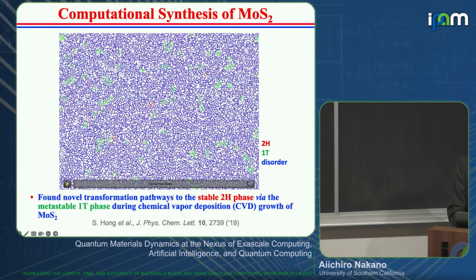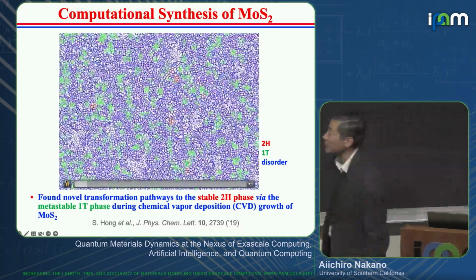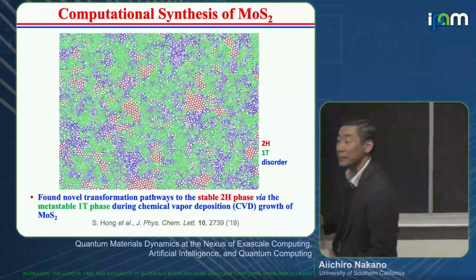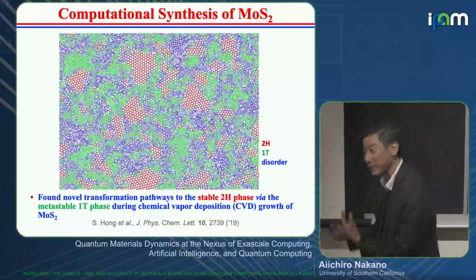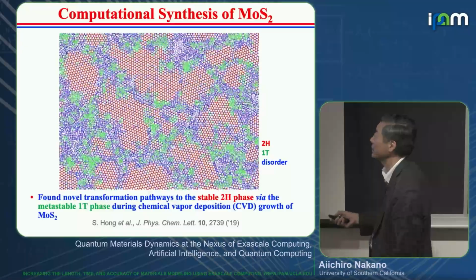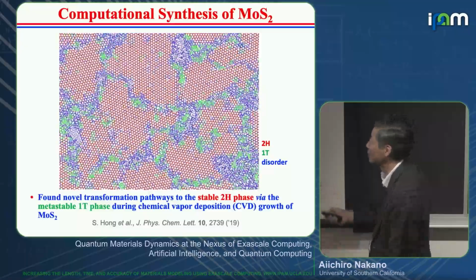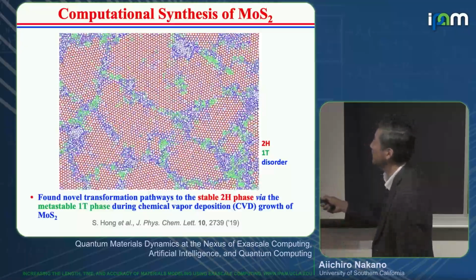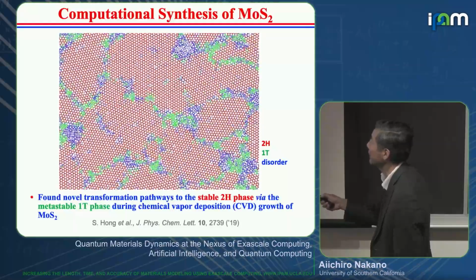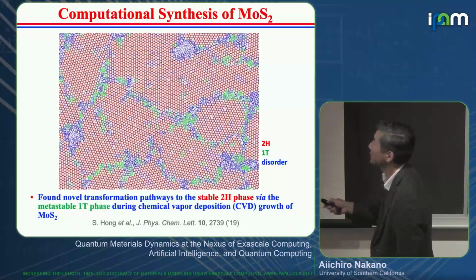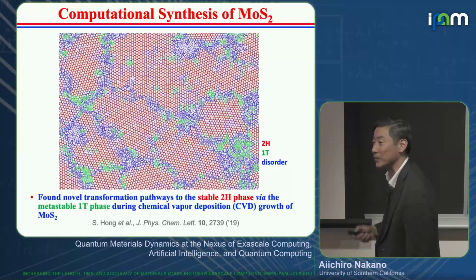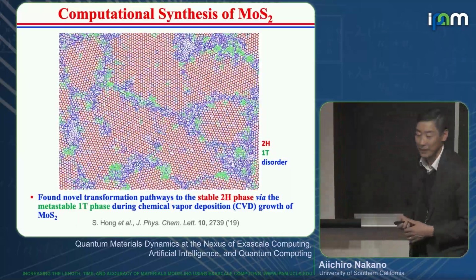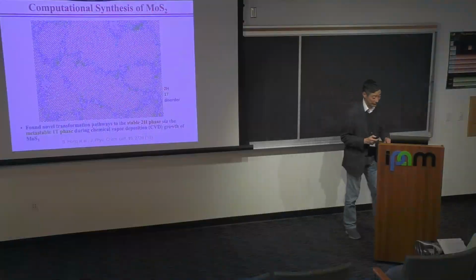So let me play a movie. You see, from random, first you see green, that's the metastable phase that is kinetically more accessible first. So it goes there, but eventually it finds the global minimum, the 2H phase, and then the grains surrounded by the grain boundary. That's the kind of realistic structure we can grow with molecular dynamics.